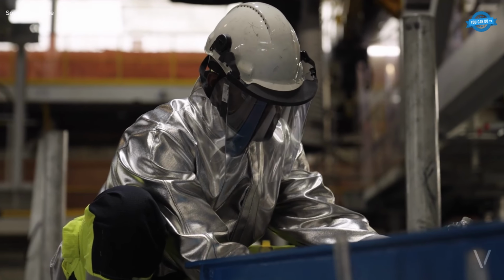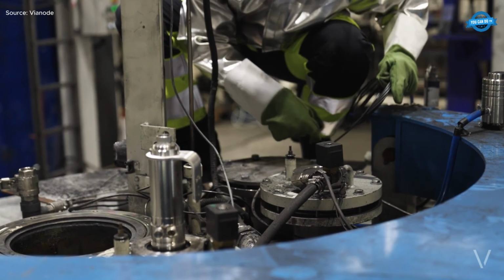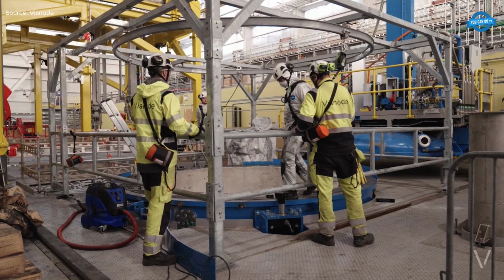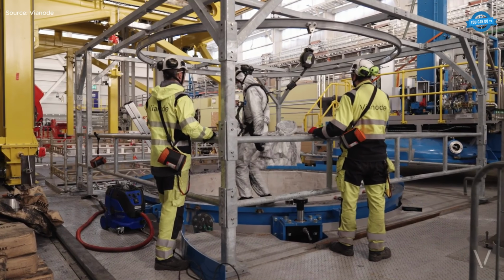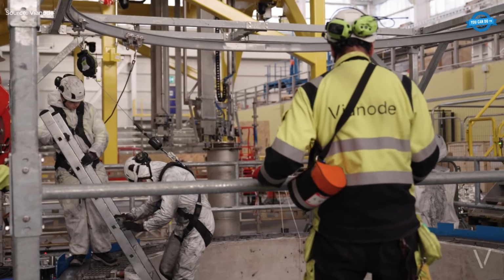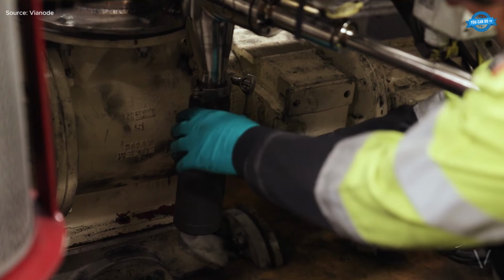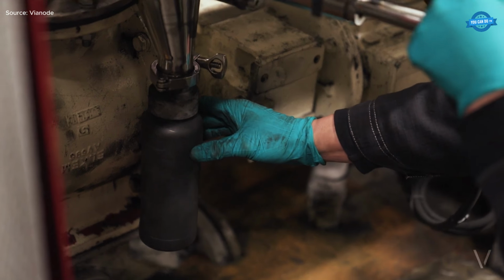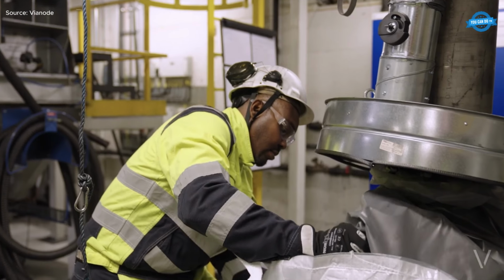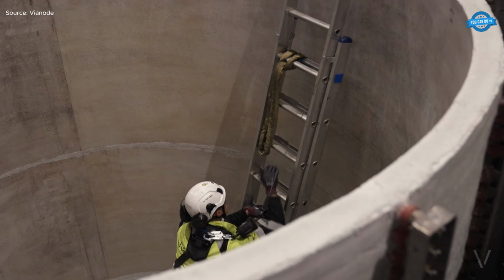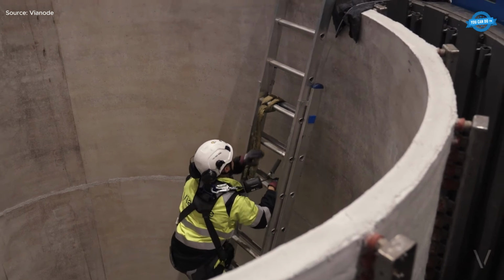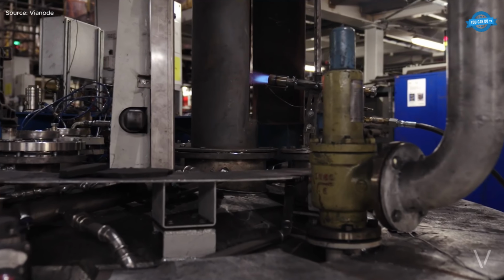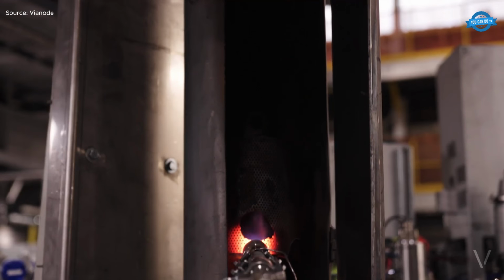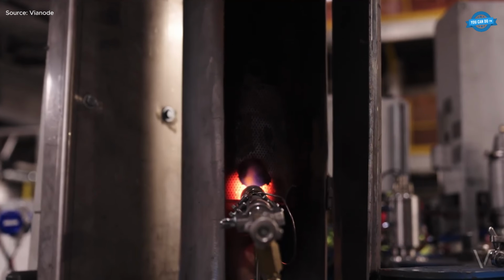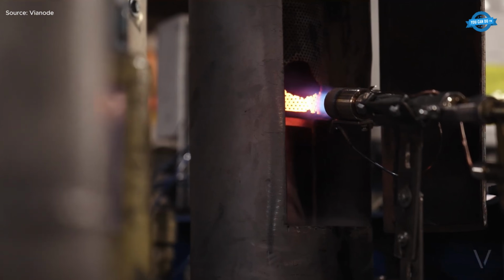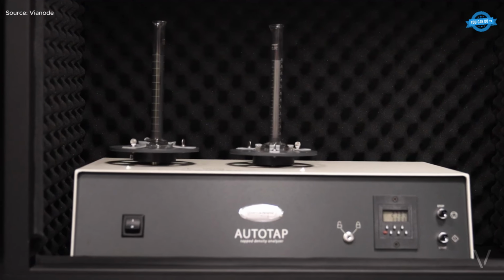In the agglomeration stage, pitch binds milled carbon into uniform granules, optimized for high-rate performance. The material then undergoes graphitization at approximately 3000 degrees C in closed, high-efficiency furnaces that transform amorphous carbon into a crystalline layered structure. Final coating with pitch enhances fast charge behavior, and rigorous sieving plus magnetic removal ensure ultra-clean, automotive-grade anode material.